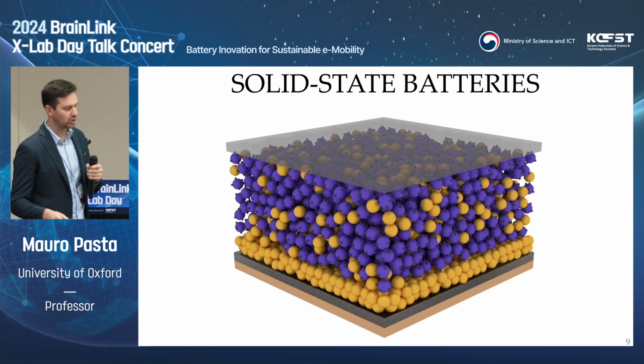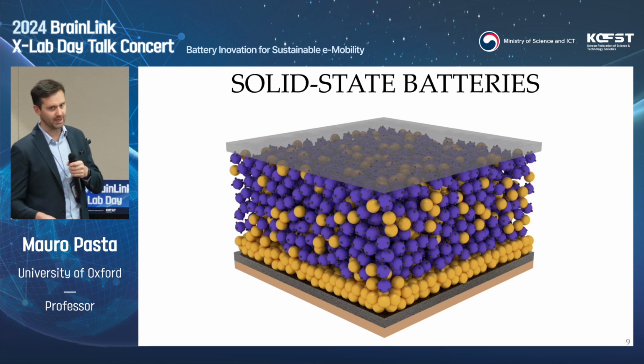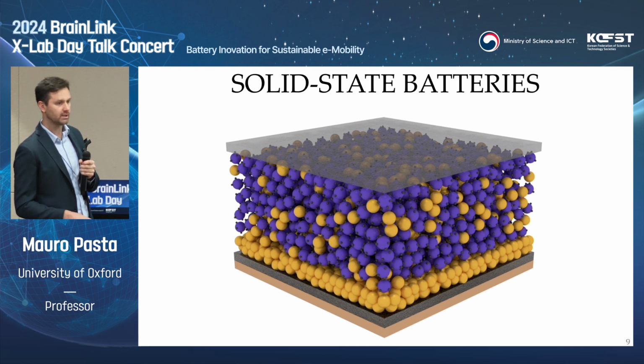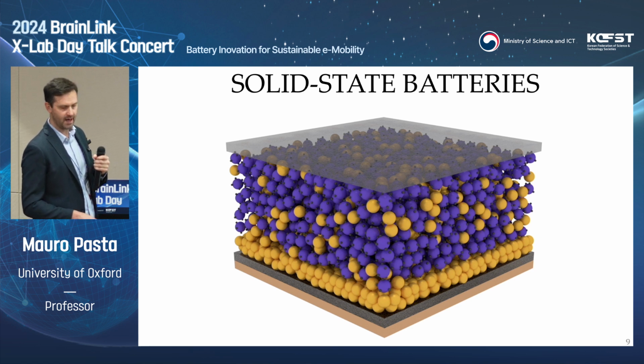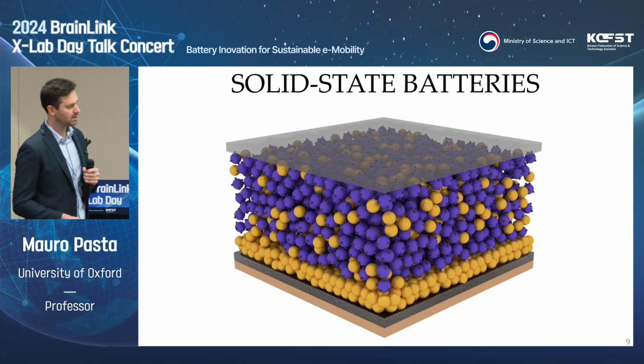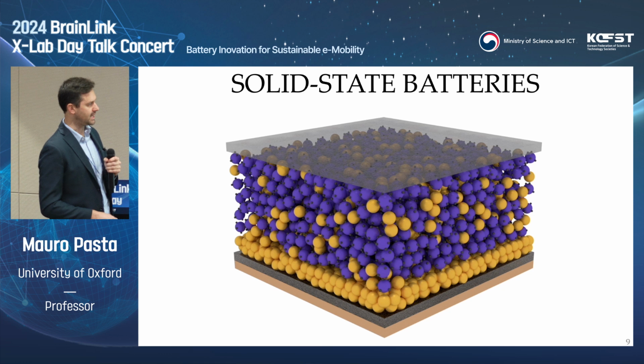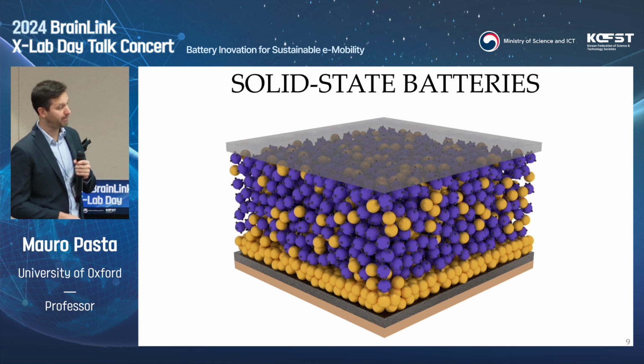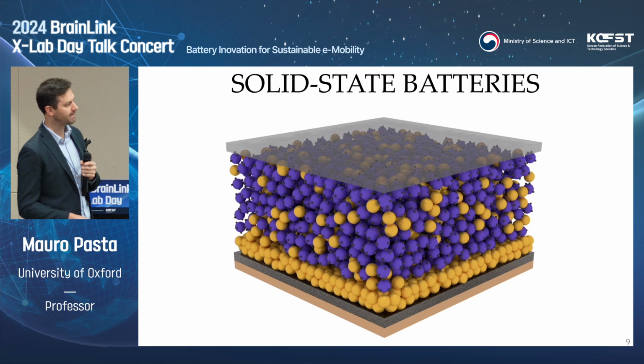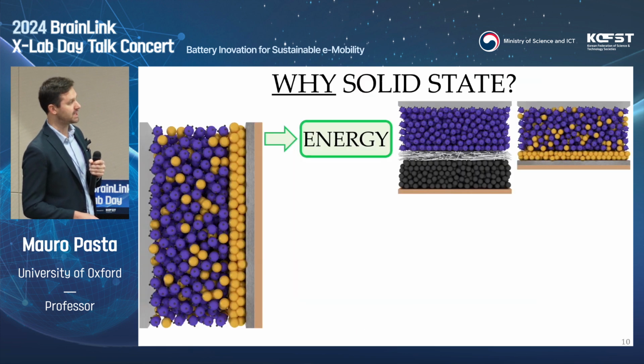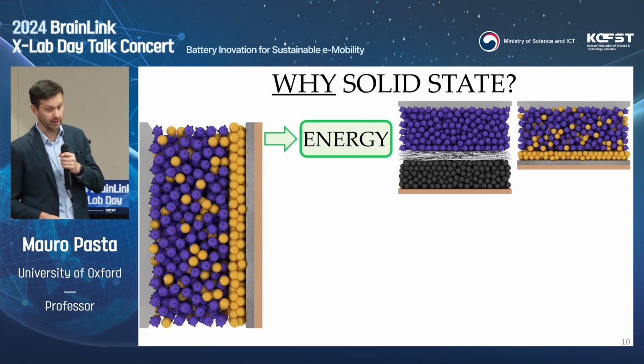There are different kinds of solid. It could be a polymer. We focus our attention on inorganic ceramic solid electrolytes, and in particular sulfide solid electrolytes, as they have the mechanical properties required in principle to stop dendrites from propagating and forming. Also because they have a conductivity that is comparable, let's say, with a liquid electrolyte or even superior. And the combination of both results in potential increases in energy density, but not only.